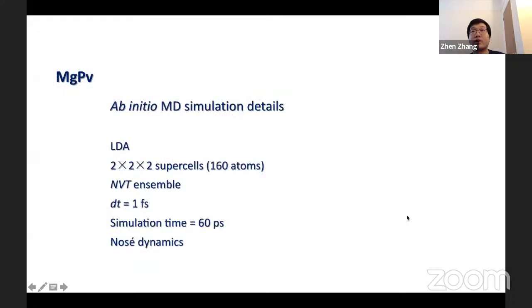Here are the ab initio MD simulation details. LDA was chosen for the exchange correlation function. 2x2x2 supercells equivalent to 160 atoms were simulated in the NVT ensemble. Each MD ran for 60 picoseconds with a time step of 1 femtosecond. Temperatures were controlled by Nosé dynamics.